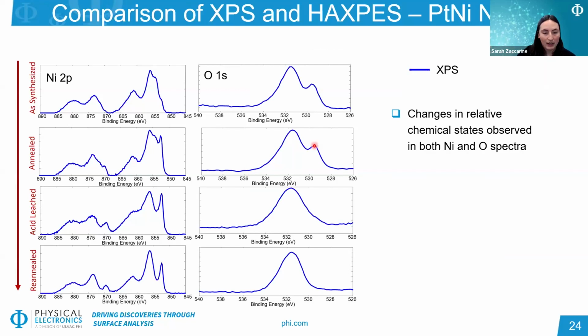So we're going to start again looking at the platinum nickel nanowire data set. From top to bottom, this is the as synthesized, then annealed, acid leached, and reannealed samples. And we're looking at the nickel and oxygen chemistry. And we see right away qualitatively that there is a clear peak-shaped change with each of these different processing steps.